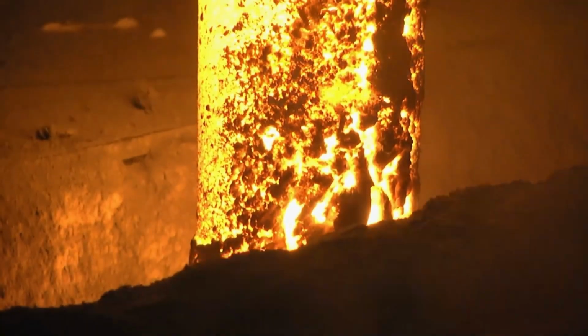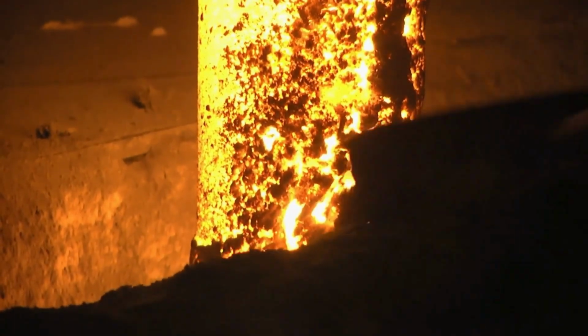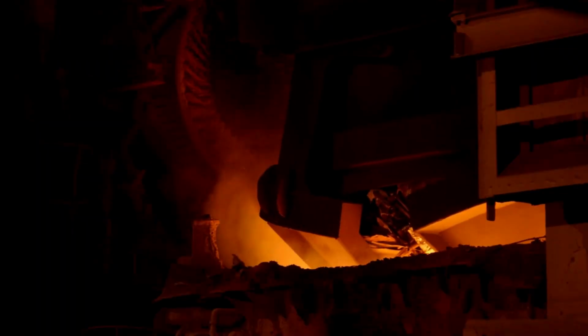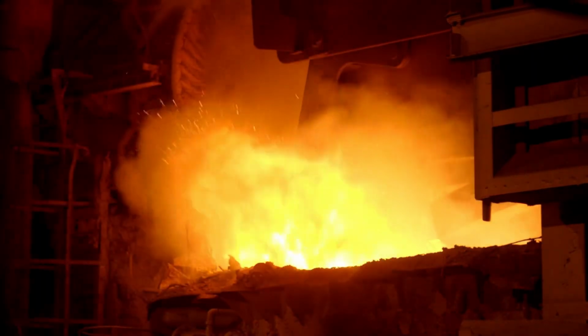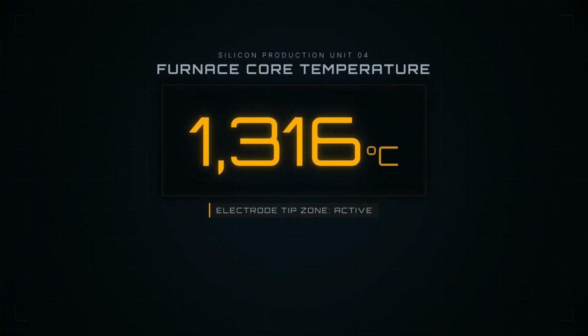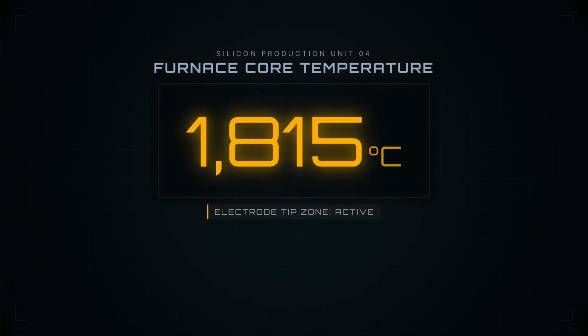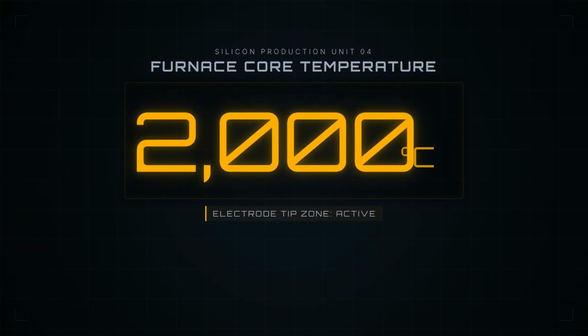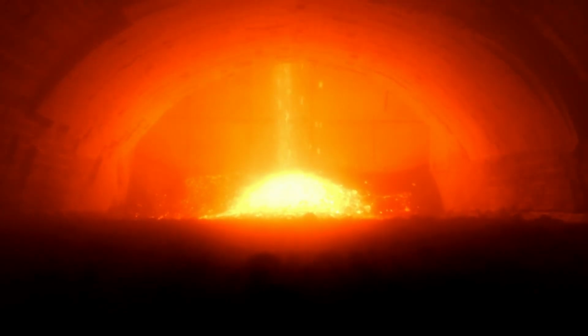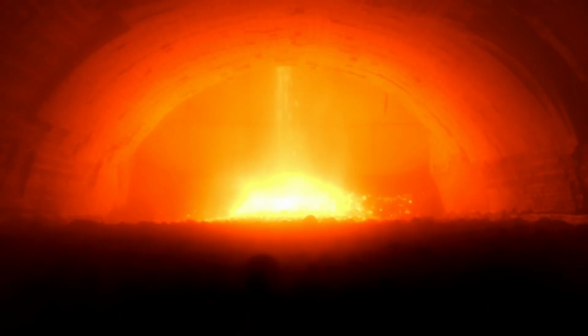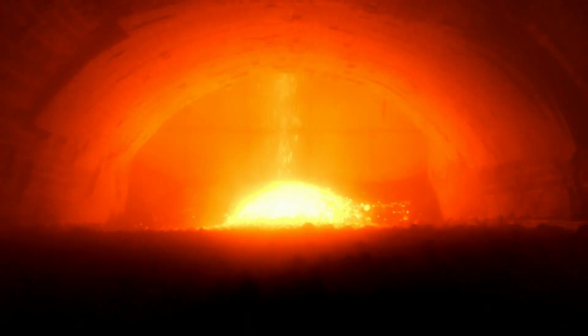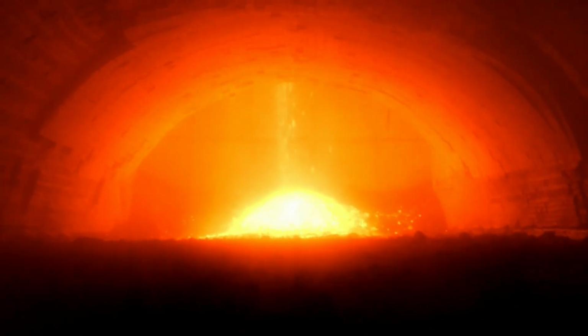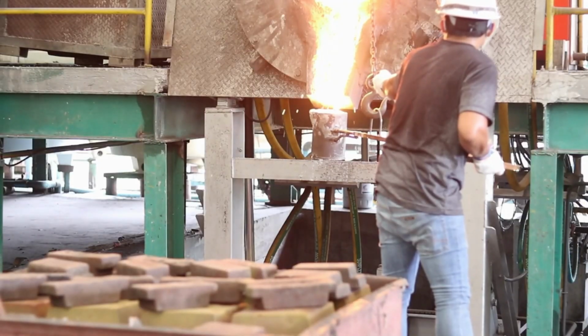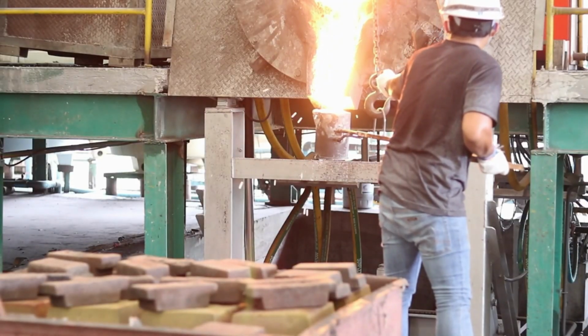Inside the electric arc furnace, massive graphite electrodes descend into the furnace charge. Electrical energy passes through the carbon-rich bed, producing intense heat. Temperatures inside silicon production furnaces can reach up to 2,000 degrees Celsius, with the hottest zone near the electrode tip. At these temperatures, silica loses oxygen, carbon becomes carbon monoxide gas, and molten silicon collects near the bottom. When the batch is ready, the furnace is tapped. Glowing silicon flows out like liquid metal.